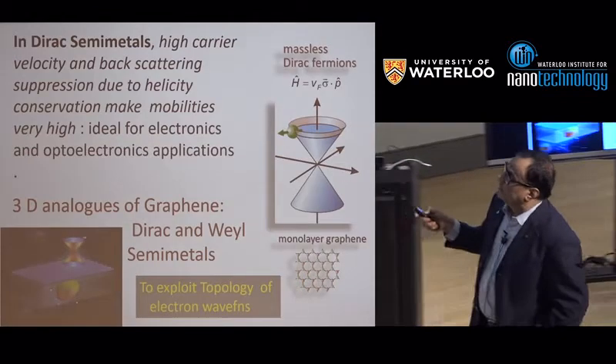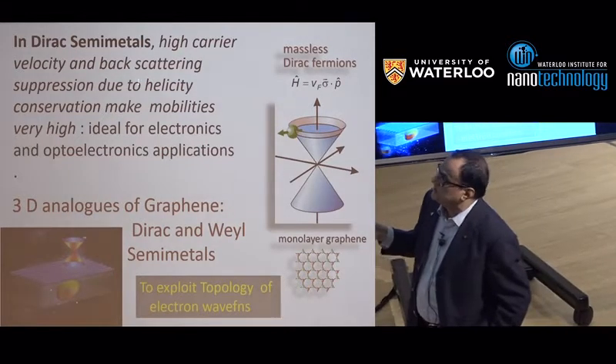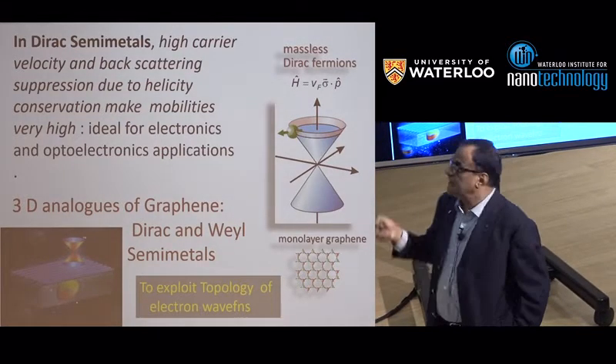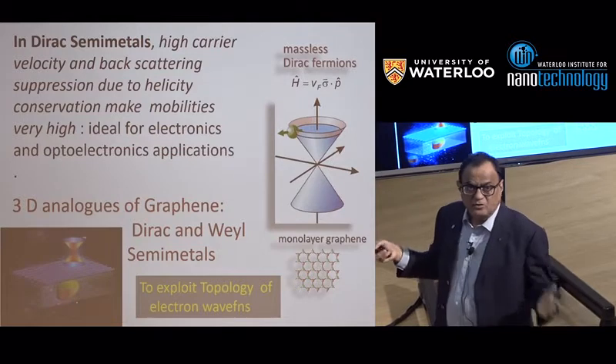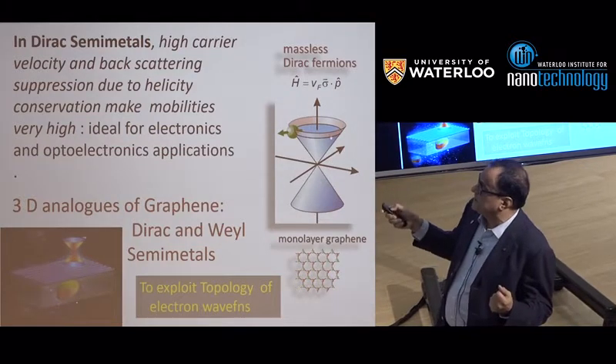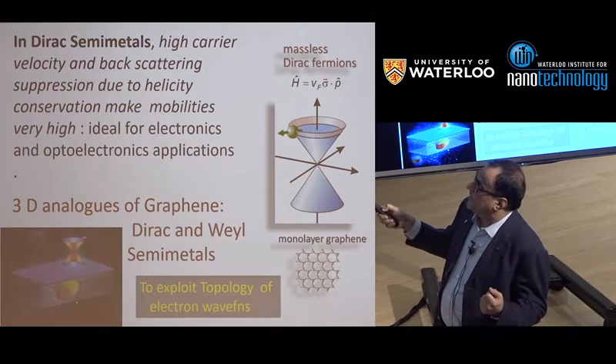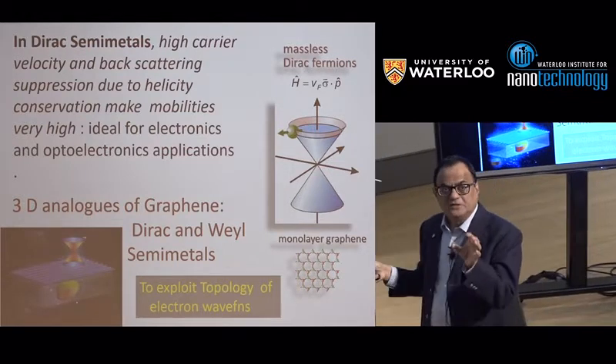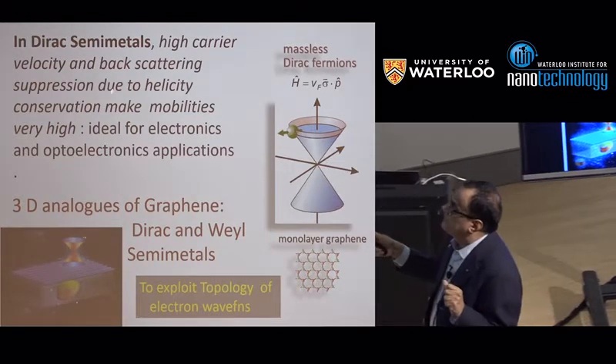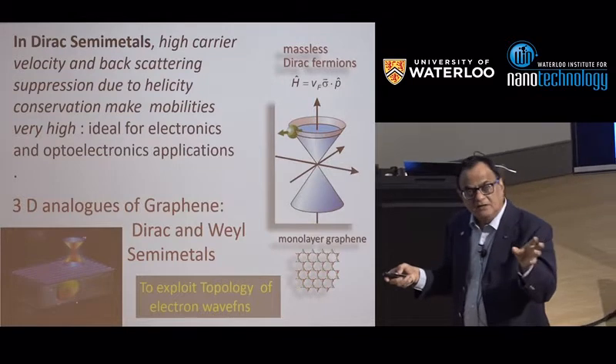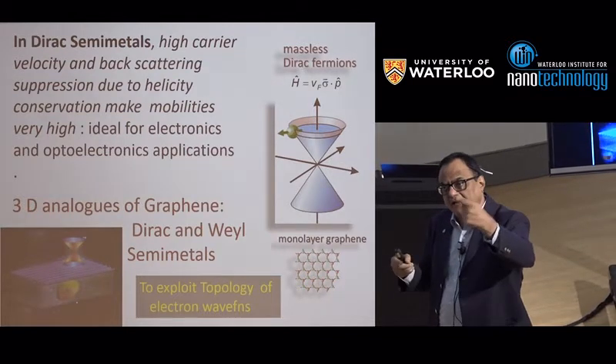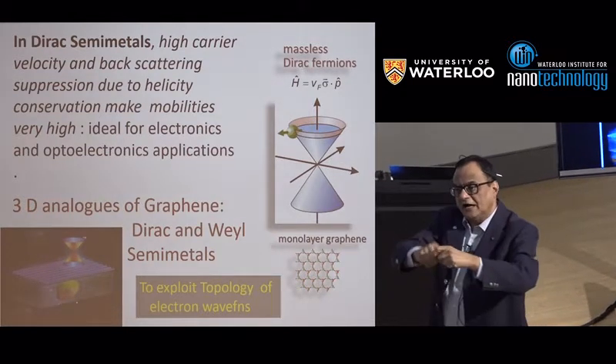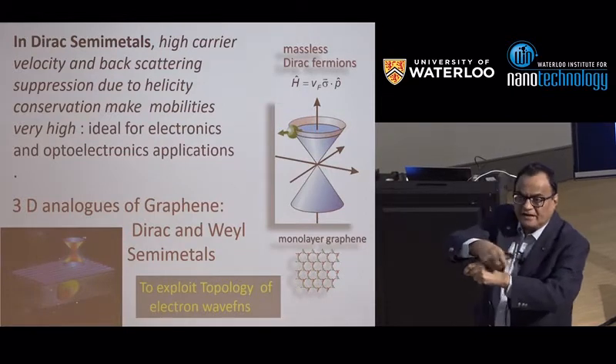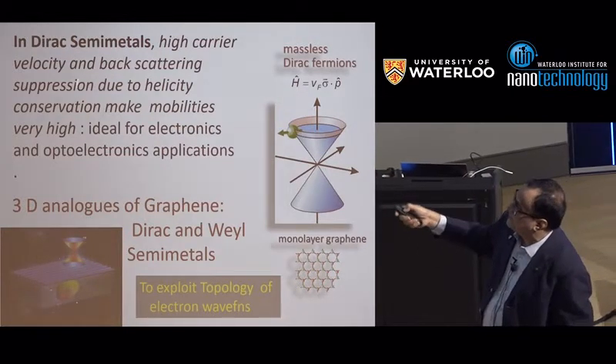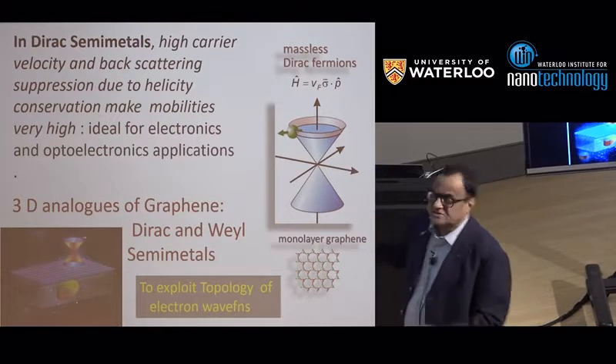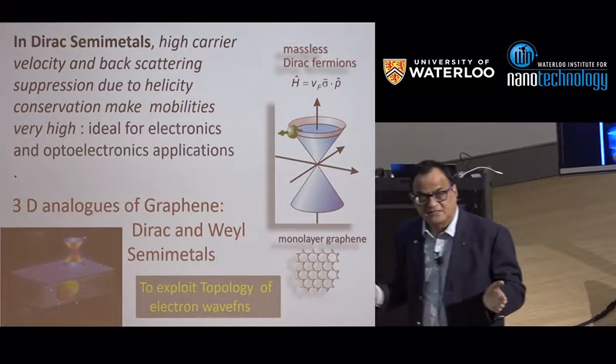And another feature which cannot escape us is that in graphene it's a Dirac electron. We all know that because the dispersion is linear at the K point, and this Dirac feature brings a very important thing, that there is a helicity conservation where the spin and the angular momentum are locked. So you avoid the backscattering, which gives you high mobility of the carriers. Even at room temperature you get high mobility of carriers in graphene.